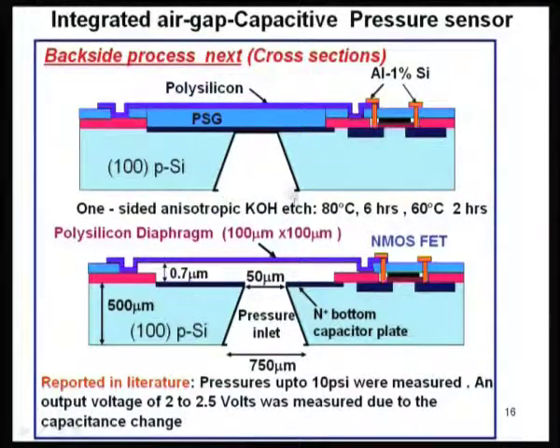You can locate this window here in the oxide precisely aligned to the center of this portion and then etch out this silicon from here using KOH etching. So, one sided anisotropic KOH etch at 80 degree centigrade for 6 hours plus, that is an etch fast, then drop the temperature to 60 degree, etch for another 2 hours, the etch rate will be reduced. So that you have got etching from this end to that until it hits this particular N plus region, etch that also down. Okay. So, what you did is you have etched out this back side completely right in this portion.